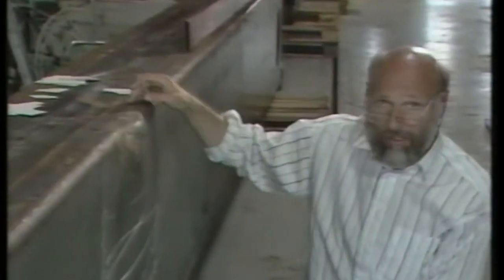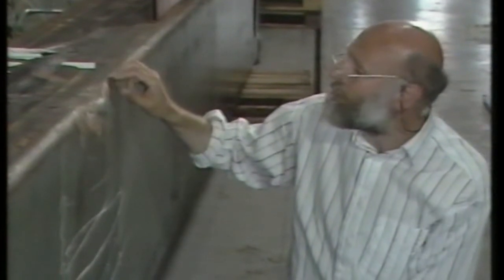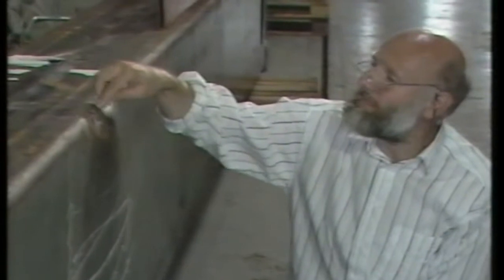Here we have what appears to be a simple defect, but it is in fact quite complicated. We have here from the beginning a manufacturing deformation, this bulge in the corner. It is superimposed on the breakdown deformation here and is to be aligned later. In this way you destroy the material even more. This means that the sum of the two deformations is quite large.